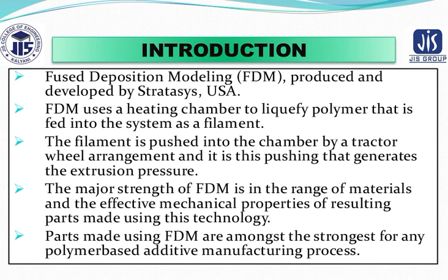Now the thickness represents the base achievable tolerance in the vertical direction, and in the XY plane the dimensional accuracy can be as fine as 0.025 millimeter, as long as filament can be extruded into the features.